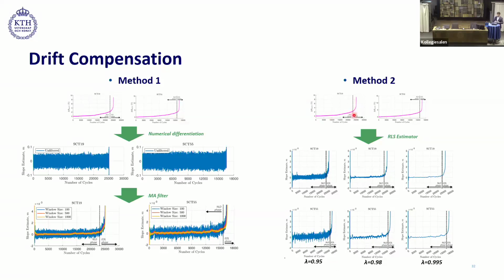Therefore, we check this for different values of lambda. And we see that at lambda 0.95, the noise is still quite high. However, it reduces with 0.995. So we see that lambda equal to 0.995 provides better output. However, it's also important to note that with increasing lambda, there are also delays. So from this contribution, we were able to finally develop a method which can be used to detect package-related failures in TO247 package.